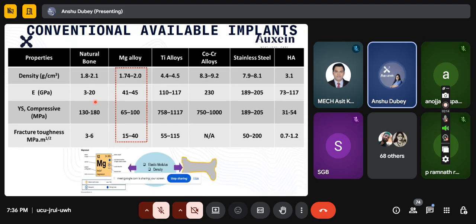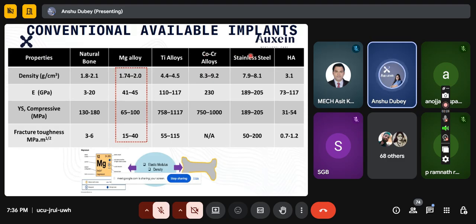This slide shows that in orthopedics, the commonly available materials are titanium, cobalt chromium, and stainless steel. But if you see the properties of these materials, such as density, elastic modulus, or compressive strength, they are high compared to the natural bone. You can see it's just 1.8 to 2.1. And for titanium and cobalt chromium, the density is huge, the elastic modulus is very huge, and the compressive strength is also very huge.